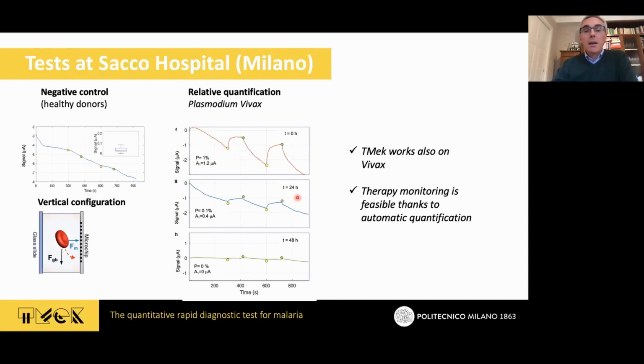What happens 24 hours after? It turns out that the signal decreases, and after 2 days, the signal is almost zero, which is a clear demonstration that we can use the quantification capabilities of TMek in order to follow the evolution of the illness stage. And this is a difference with respect to the rapid diagnostic test. So we have something which can be really quantitative.